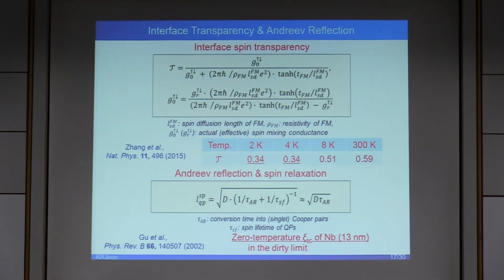For the transport length of dynamically driven spin-polarized quasiparticles in the diffusive low temperature condition, one has to take into account the conversion time of quasiparticles into singlet Cooper pairs by Andreev reflection, in addition to their spin lifetime. Considering that the conversion time is much shorter than the spin lifetime, since Andreev reflection is fundamentally an interfacial conversion process, this equation can be simplified to the square root of the diffusion coefficient multiplied by the conversion time, which can therefore be comparable to the superconducting coherence length. In fact, we found that the estimated spin transport length of approximately 20 nanometer at 2 Kelvin is on the order of the zero temperature coherence length of niobium in the dirty limit.